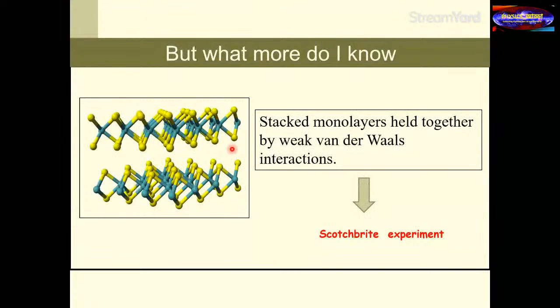But if I look at it from the side, what I see is that these materials are slightly different. Whatever I showed you from the side is now looking like this. That is, you have the central layer, which has the transition metal atom. You have the top layer, which are the selenium atoms or whatever anions you have, and a bottom layer of this. So this, if you looked at from top, forms this hexagonal lattice.